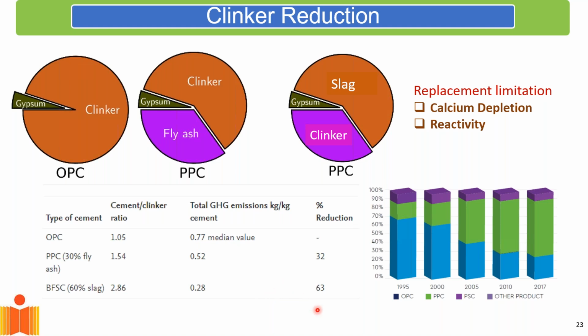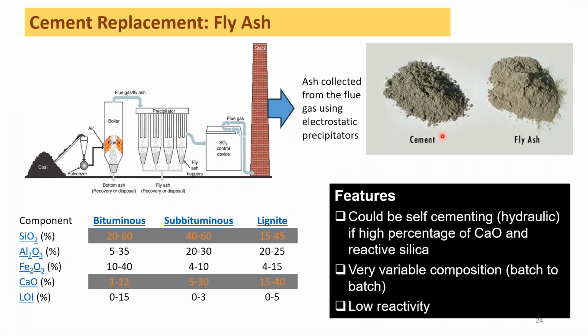Now, of course, the issues here, and I'll show this a little later, is the calcium depletion. I cannot indefinitely keep adding slag or fly ash into the cement, because I'll deplete the calcium in the system. And there is also a big uncertainty in these two materials, fly ash and slag. They're not manufactured materials, they're waste materials. I cannot control the composition of these materials, and therefore the reactivity of these materials oftentimes dictates how much of this material I can replace in cement.